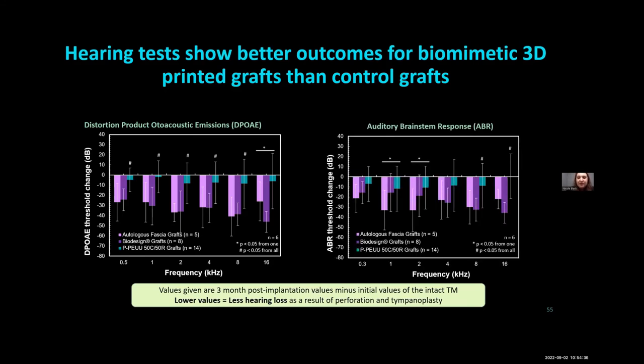We see the same thing with auditory brainstem response. And interestingly, we even had a couple animals who at the highest frequency had better hearing at that high frequency after the tympanoplasty than they did with their original eardrum. So this is suggesting we could possibly even use microstructure in the future to improve hearing and to possibly modify the structure of the eardrum to create a more orthotropic structure for sound conduction.